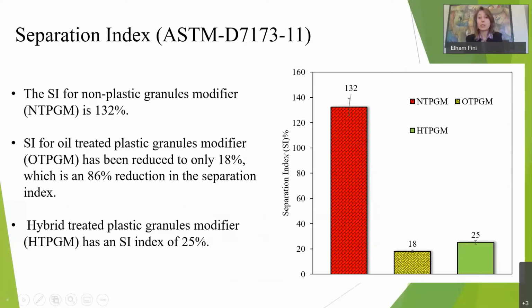So separation index, or what we call SI here, is 132%. That was too high, and no one will accept such a high segregation and it will not be approved even for the road construction. When we did the oil treatment, we ended up getting 18, and with the hybrid treatment, we got 25, which was way better than what we started with, which is another evidence that the surface energy did its job.